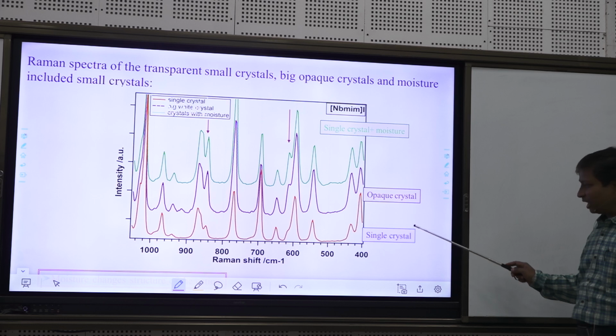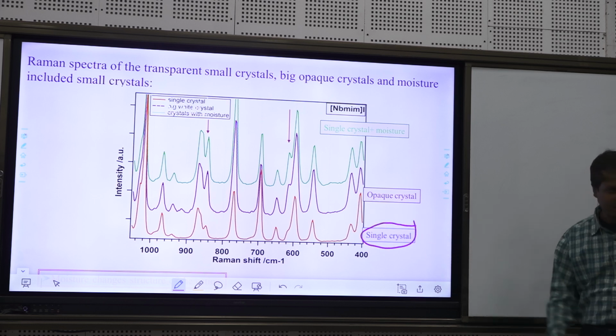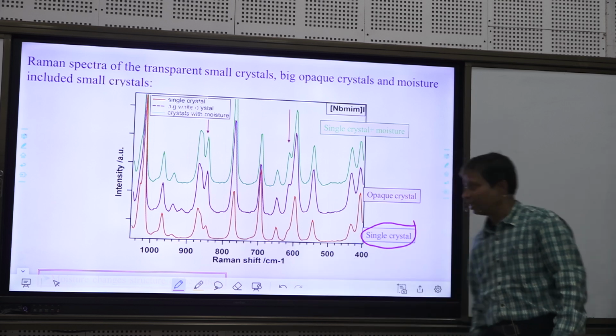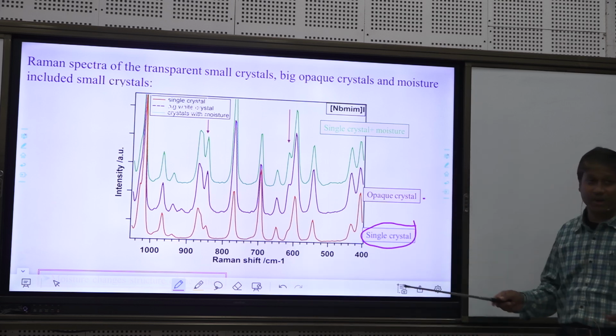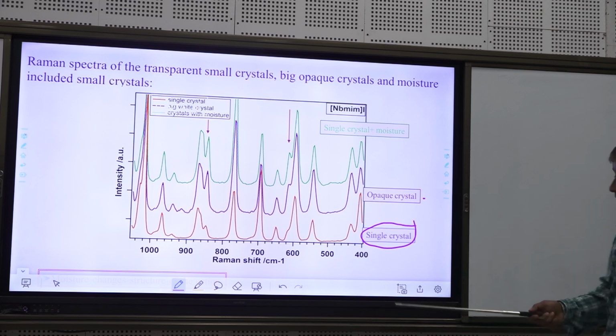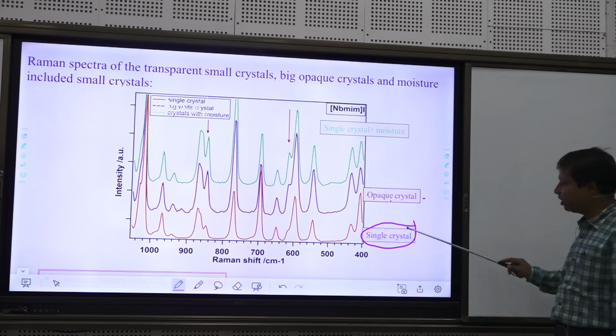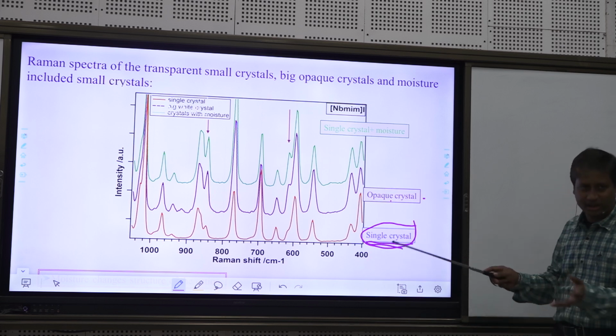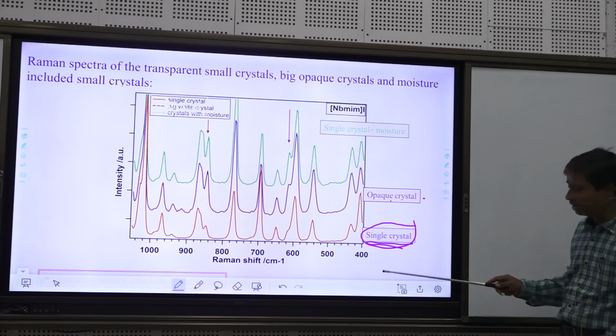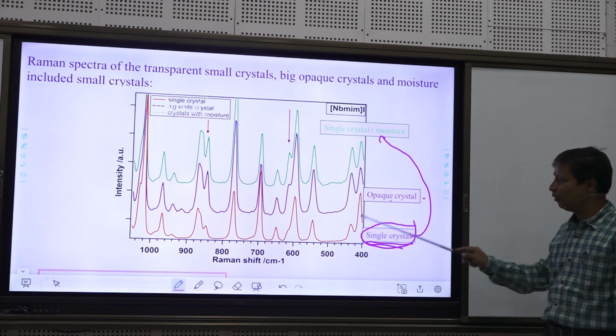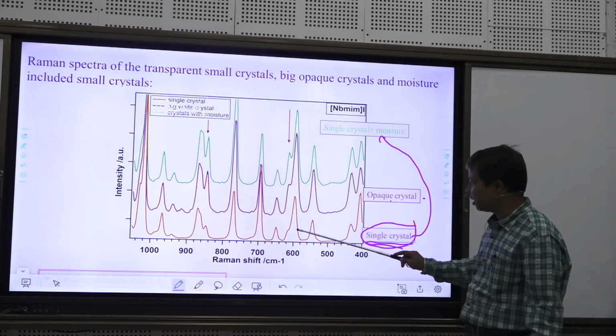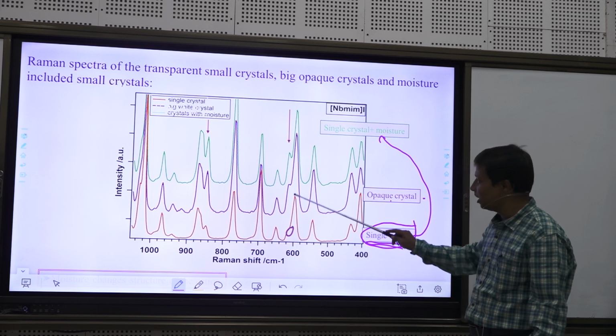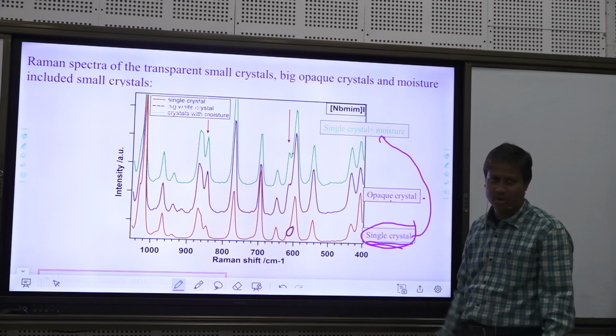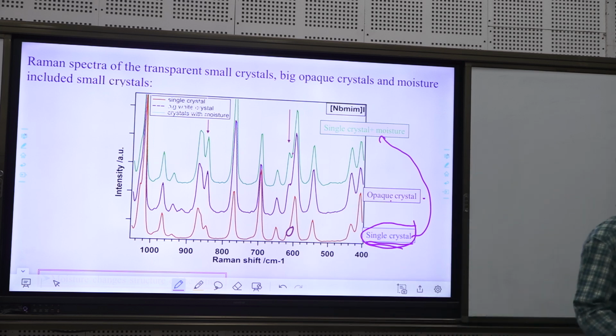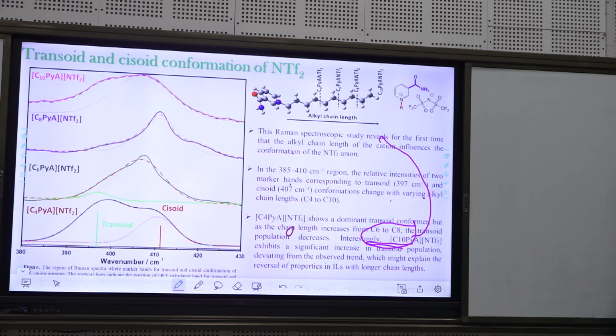So we started with a pure single crystal in which water is not there. We took the Raman spectrum, and then we took the Raman spectrum of the opaque crystal, which happened suddenly. We took this opaque crystal, and then we intentionally exposed the single crystal to the air for a few seconds, and we took the Raman spectrum, and we found that for the single crystal this marker band was almost not there, and in this case it is prominent, and here also prominent. So what we have observed is because of the exposure to moisture. So simply by studying Raman spectroscopy, we can do this.